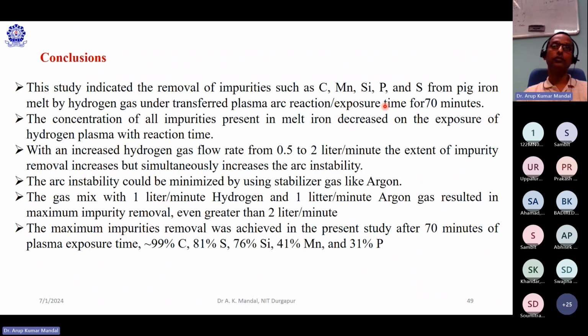And to maintain the high temperature for the effective desulfurization, what is the requirement? The prerequisite is that the arc should be a smoother arc. A continuous arc is required. Otherwise, if the temperature is fluctuating at the top surface, the sulfur removal will vary. So from this study, as I have discussed, up to 99% carbon, 81% sulfur, and 76% silicon, and 41%